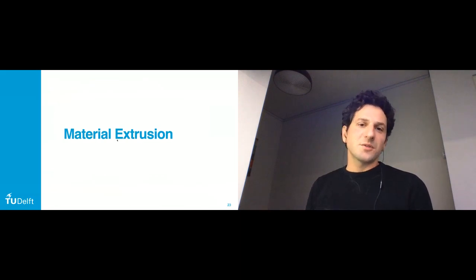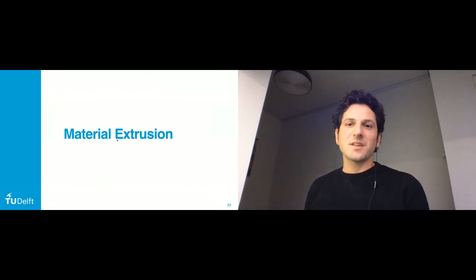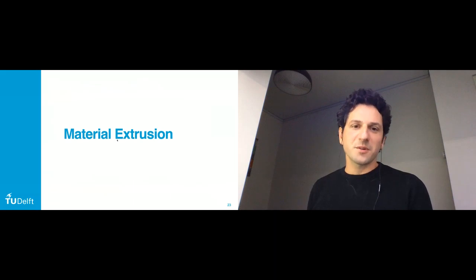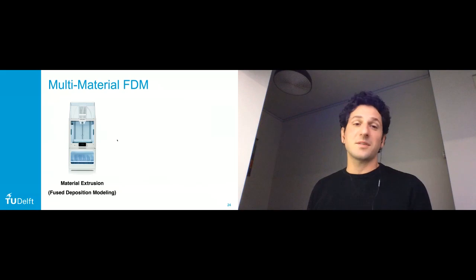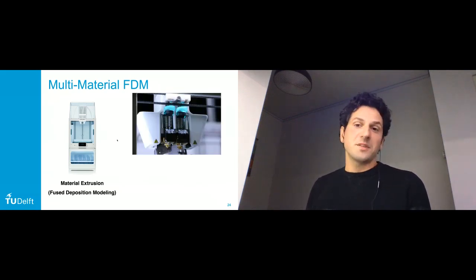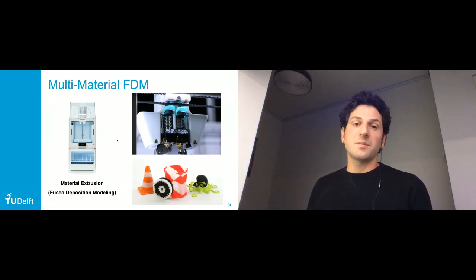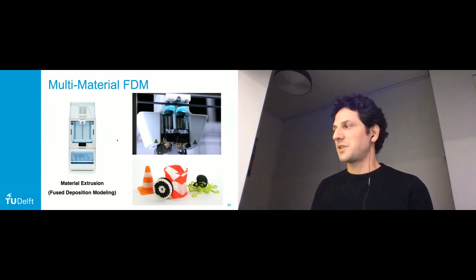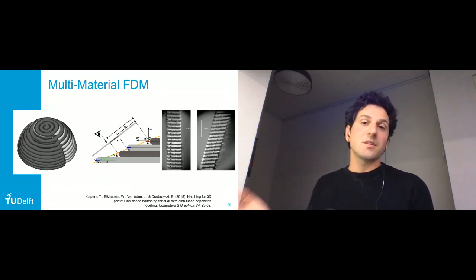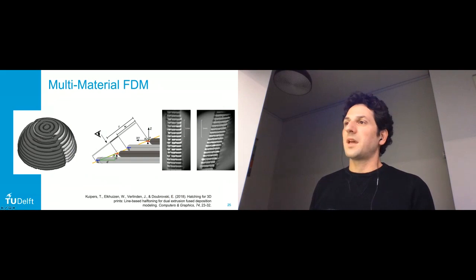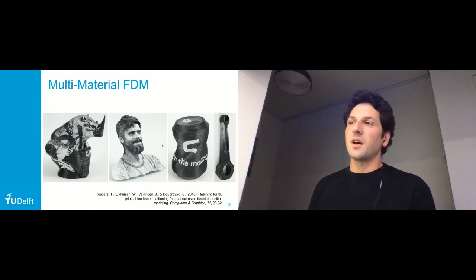And just to highlight, it's not just material jetting where these kinds of technologies can be applied, or where micro-scale additive manufacturing can be applied. There are also opportunities to do that with, for example, material extrusion. As Nicholas already explained, there are 3D printers that can create multiple material parts. And again, usually the different regions of materials are assigned to different areas with sharp transitions. However, these printers are very good at, for example, alternating having one layer printed in one color or material and the second layer in another. And that also means that we can slightly offset the extruded printing path to have, for example, light material be more visible on the outside, and that creates variations in grayscale. While still using just two materials like black and white, you can still achieve variations of colors in between.